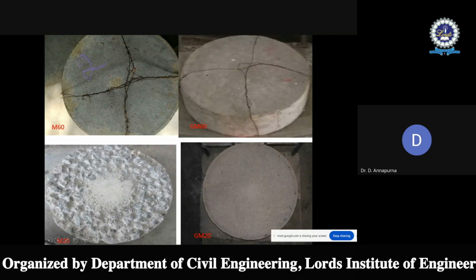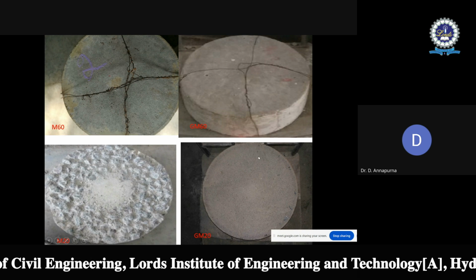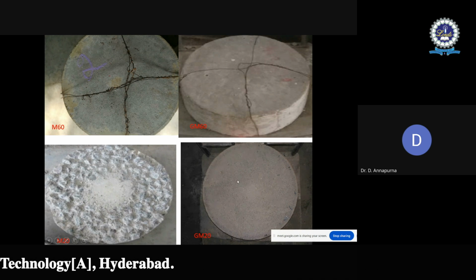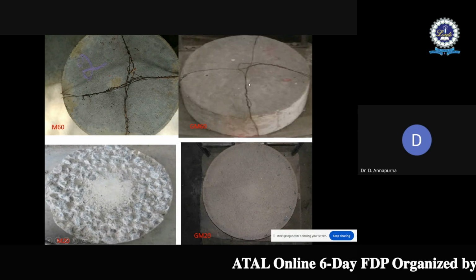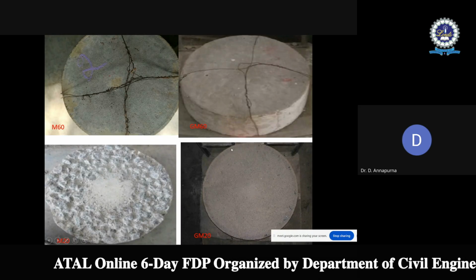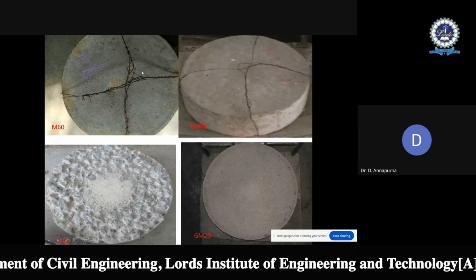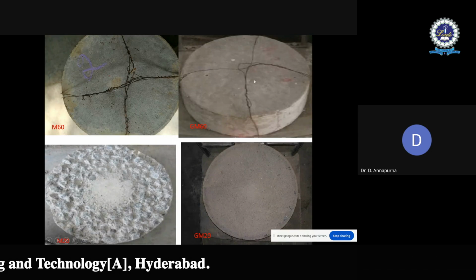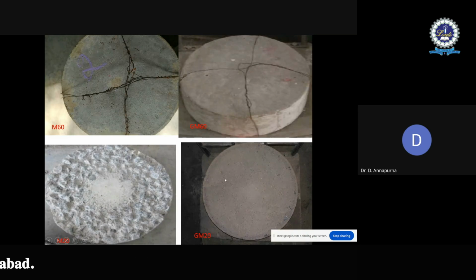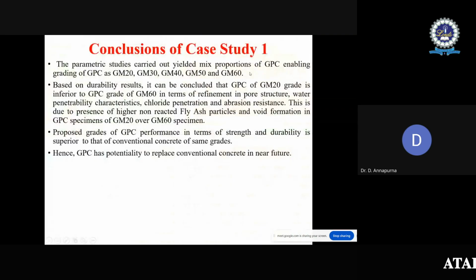When it comes to GM20, it shows superior behavior compared to the conventional concrete, because after the abrasion test it is not showing any trace of aggregate, and still intact behavior is seen with GM60. So geopolymer concrete specimens are showing superior behavior with respect to abrasion characteristics. And GM60 shows still more superior behavior compared to GM20 because of high strength.